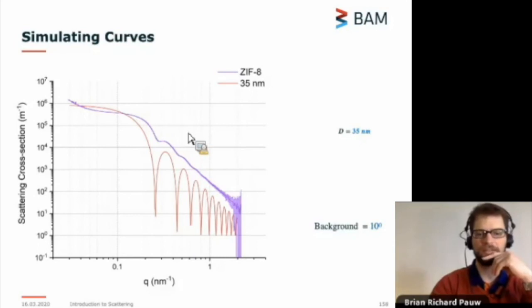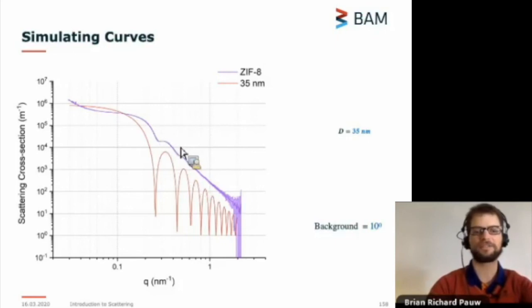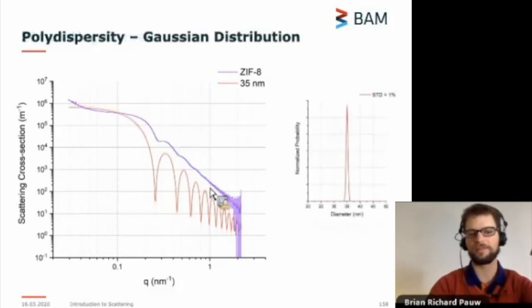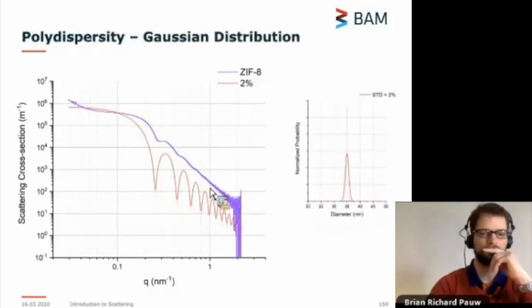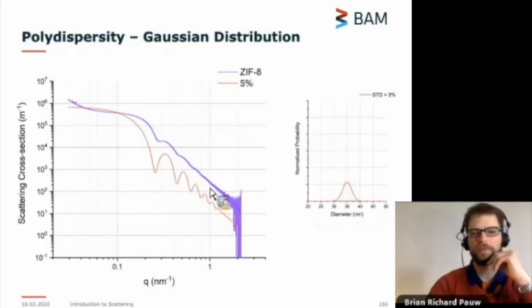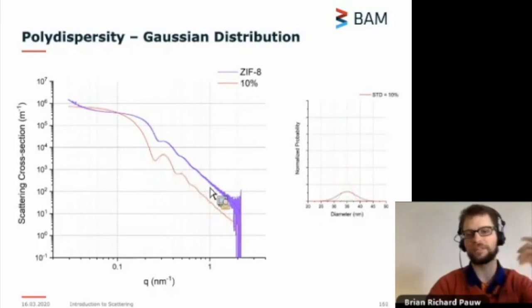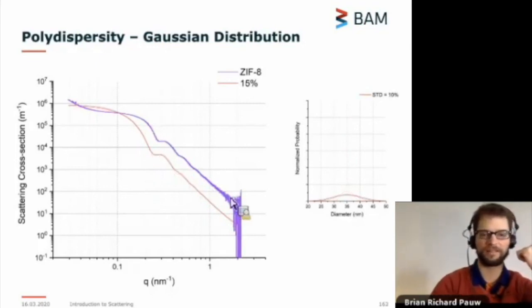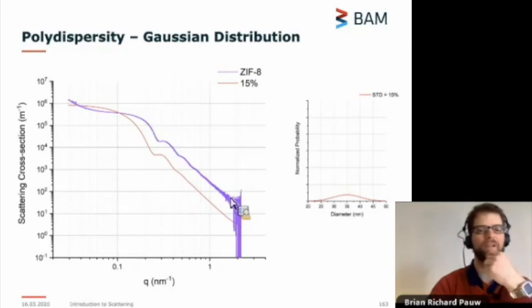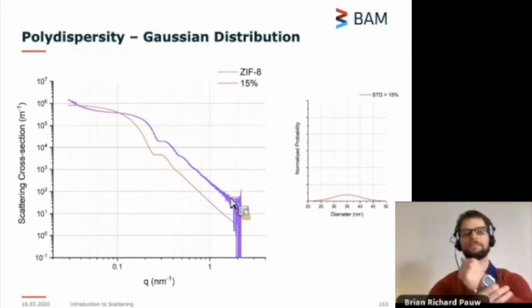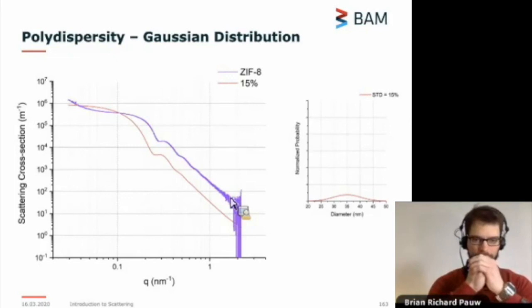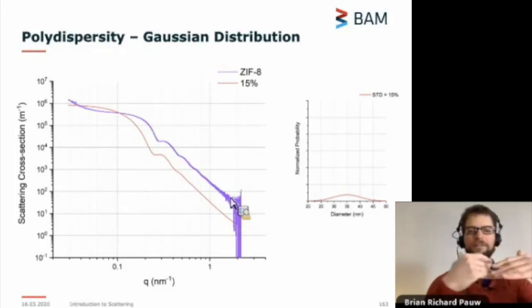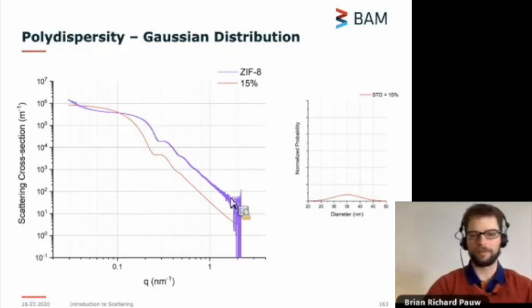And the reason they're not there is because of polydispersity. So once we start adding size distributions, these features really start disappearing. And it's when we hit size distributions of 15%, so standard deviations of 15%, that we start getting a dampening, which sort of approximates this structure. So that way we can start getting closer and closer to describing our measured signal.